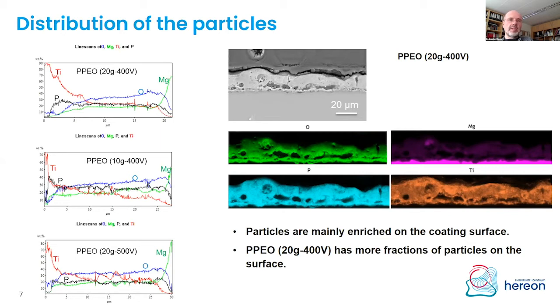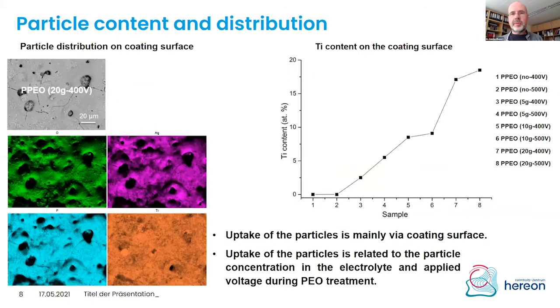Basically, you are increasing continuously the titanium dioxide concentration on the surface. And looking at the mapping and also at the line scan, it is quite obvious that most of the particles are incorporated via the surface. They are sticking in melt pools on the surface and are immobilized there. However, there is titanium dioxide throughout the full layer. And this indicates that there is a chance to incorporate them via the open pores, and they can reach even the interface. But for the photocatalytic properties, it is more important that they actually stick at the surface.